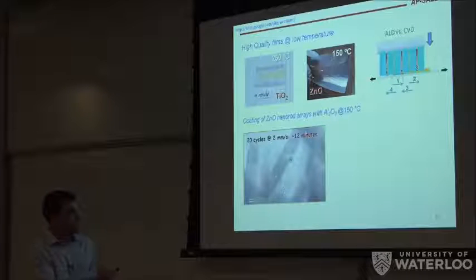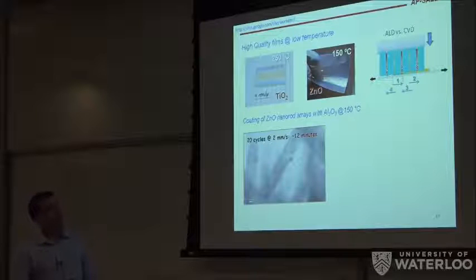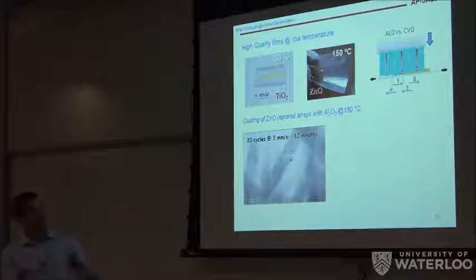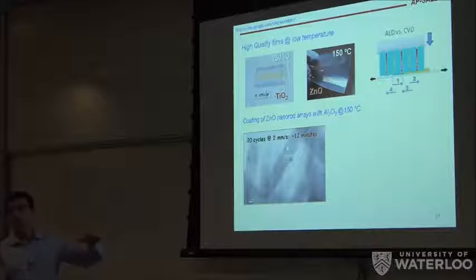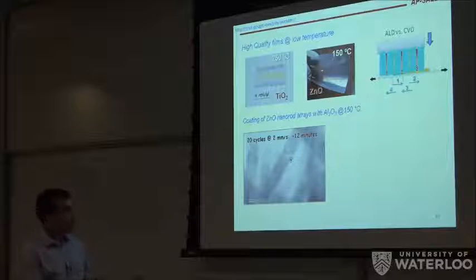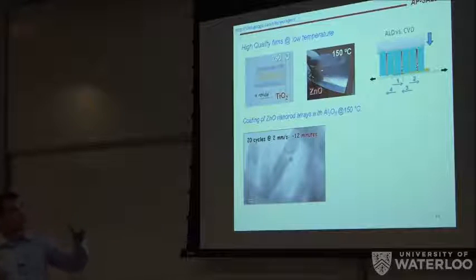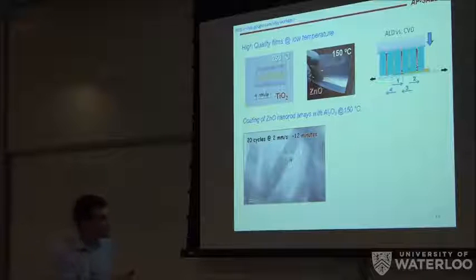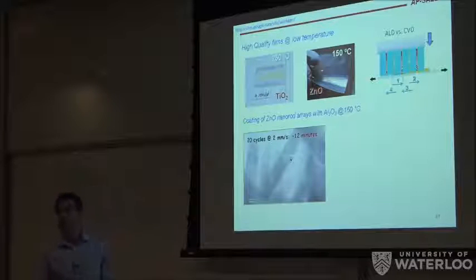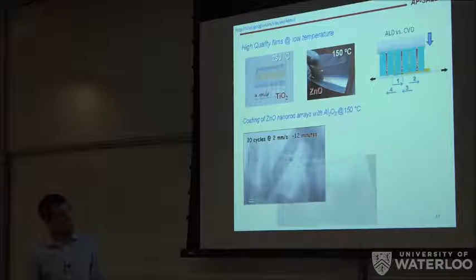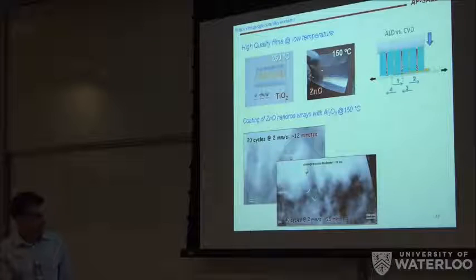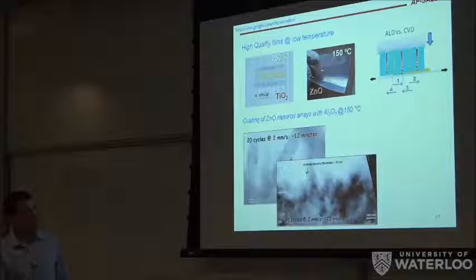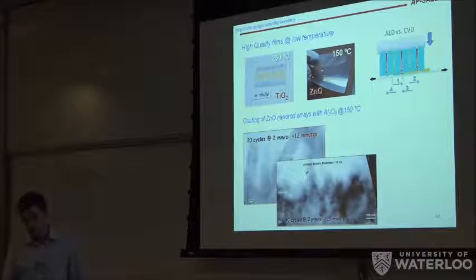In this case, we tried to coat zinc oxide nanorods, which were electrodeposited, with a thin layer of aluminum oxide. And you can see here, using the ALD conditions, we did 20 cycles at 2 millimeters per second. That's the scan speed. And of course, it took 12 minutes because we were doing it slow to give time for the surface to saturate. But you can see, or maybe you cannot see, but believe me, you have here 5 nanometers of aluminum oxide, which is conformal on the nanowires. We did, of course, twice the number of cycles to confirm that we get a thicker film. And you can see here, this is still very nice, conformal, homogeneous. But of course, it took 25 minutes, so not that fast.